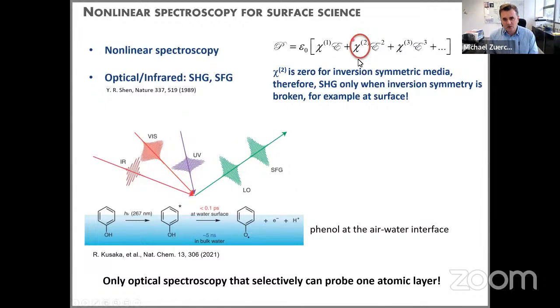I should also say that these terms are actually quite small in magnitude compared to the linear response of a medium. This is why one needs very intense or very strong electric fields, hence requiring lasers, to observe these second order nonlinear responses. However, with the birth of the laser and the finding of second harmonic generation and then the development of second harmonic spectroscopy, this has become a really important tool in surface chemistry. But one caveat here is that one can study the properties of a molecule, say the orientation and some of the chemical properties. However, one does not necessarily get information about specific elements or specific contributions to the signal, because one really probes the valence states.